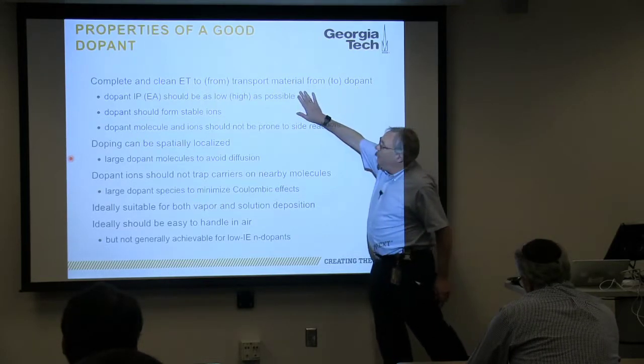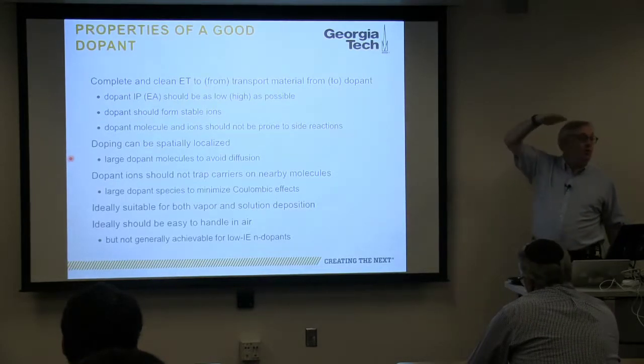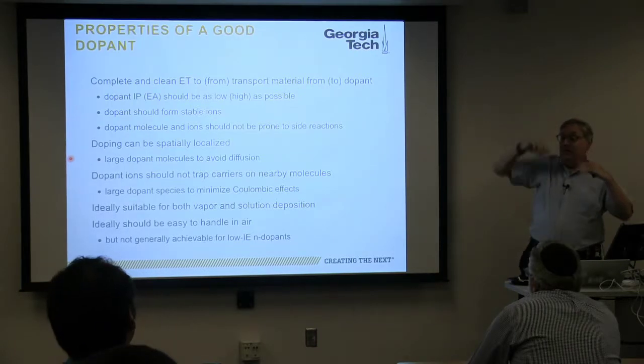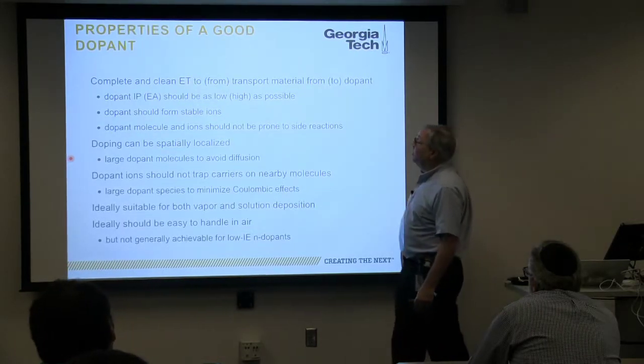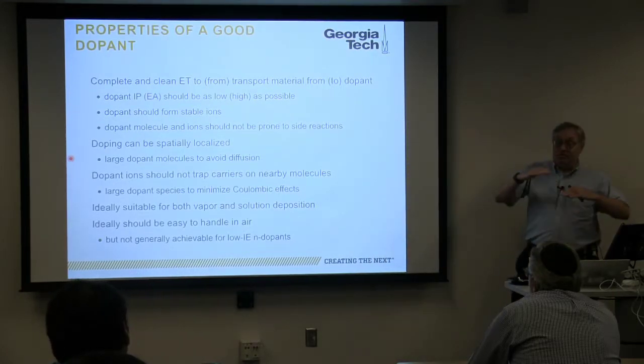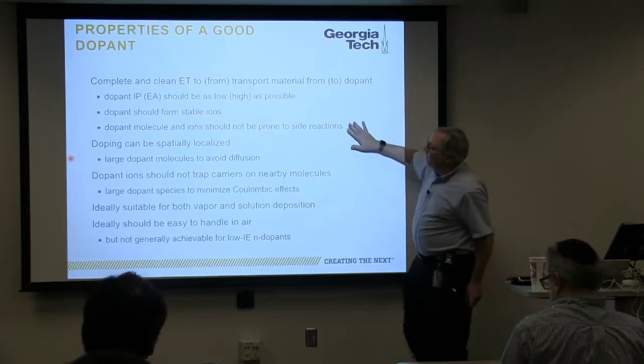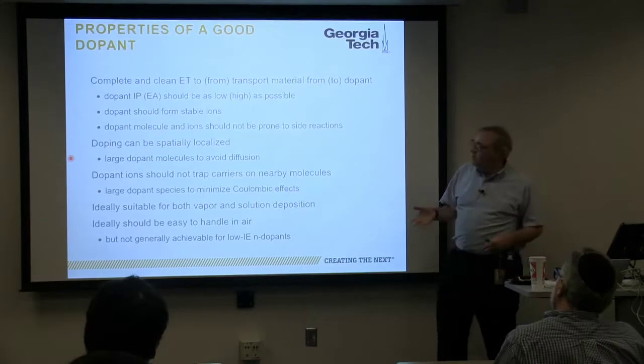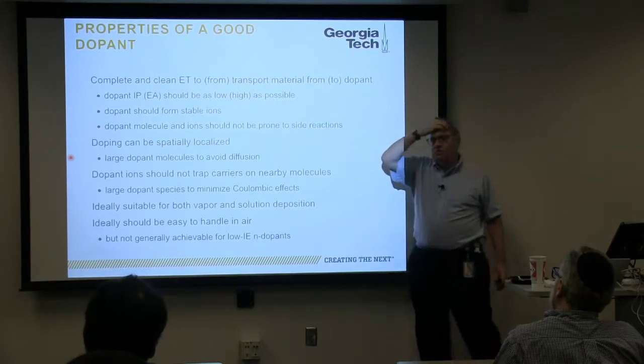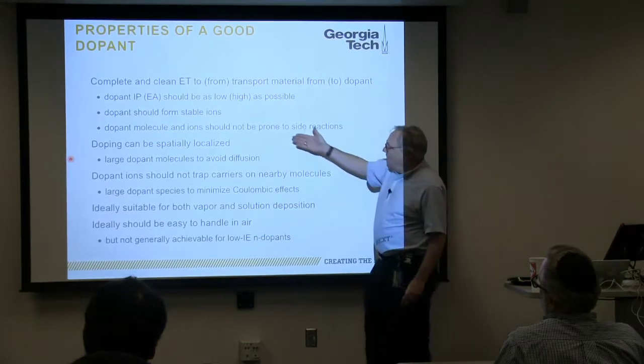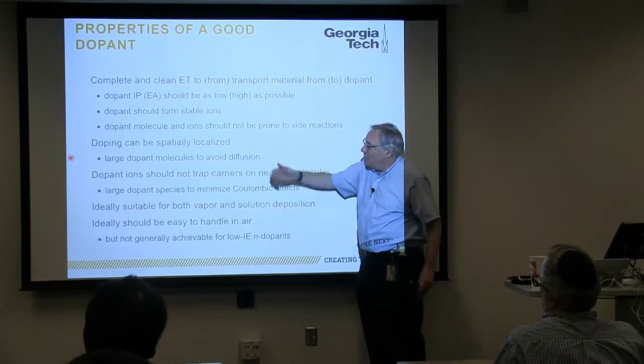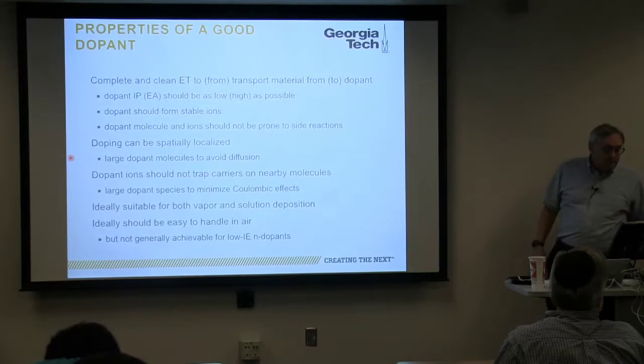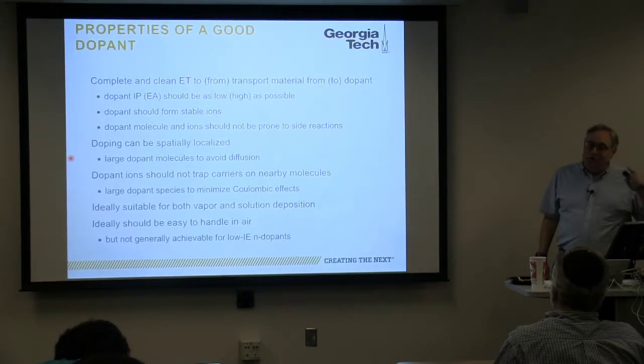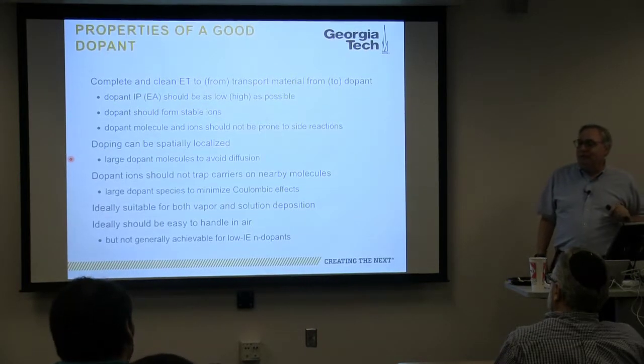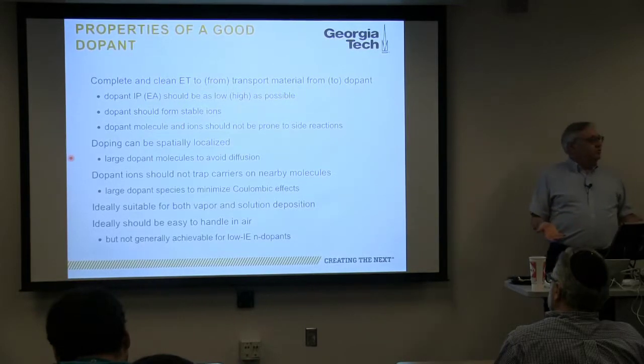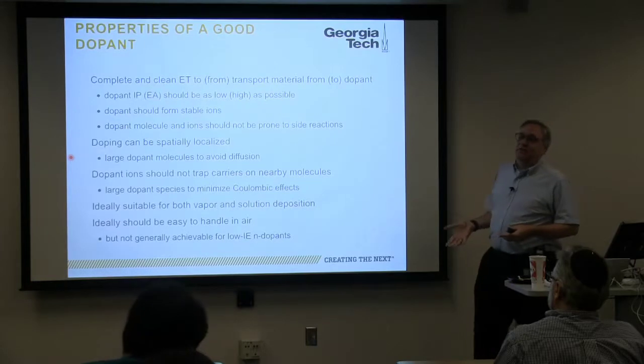We want, therefore, the ionization energy of the dopant to be as low as possible if we want to dope something that has a very low electron affinity, okay? Or we want the electron affinity of the dopant to be as high as possible if we want to take an electron from something that's very hard to oxidize, okay? We don't want the dopants themselves, the molecules, to have side reactions. We don't want the ions that we create, once we dope, to do side reactions, okay? We may want to, if we have a multi-layer device, be able to spatially localize these materials in the layer that we want. We may want these things not to act as traps, although you can imagine situations where you want to control the number of traps. And we'd like to be able to deposit them both from solution and from vacuum. And ideally, we'd like to handle these materials in air, okay?